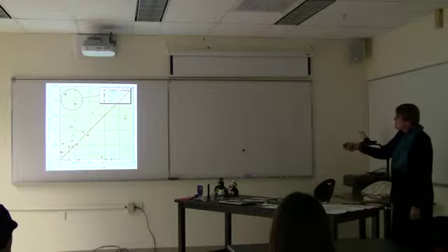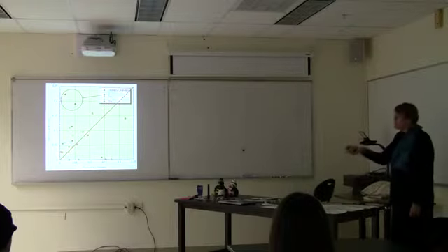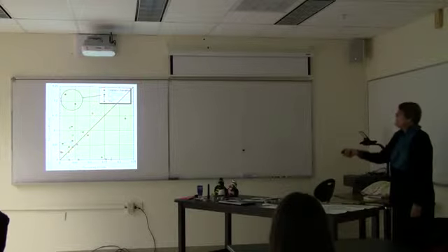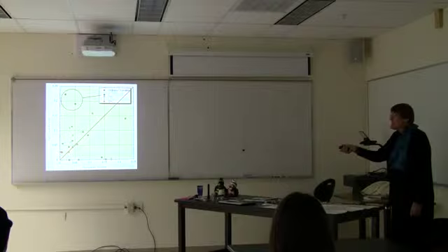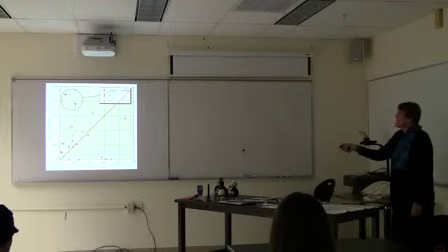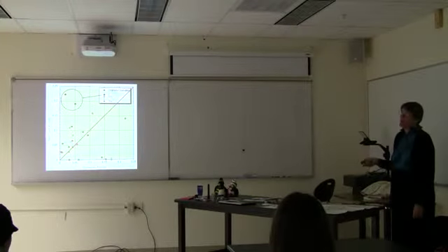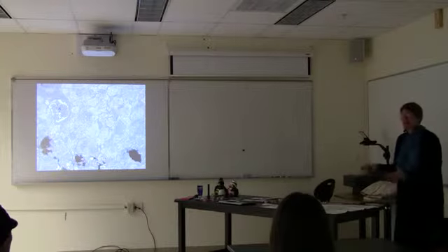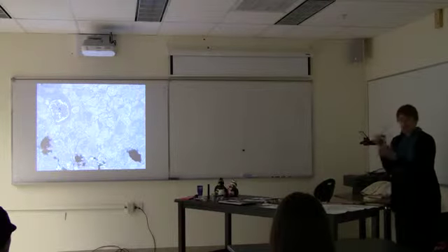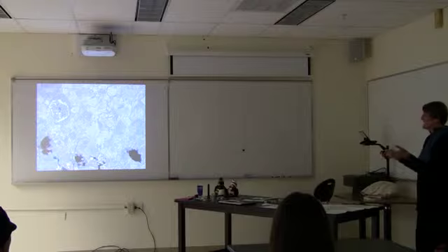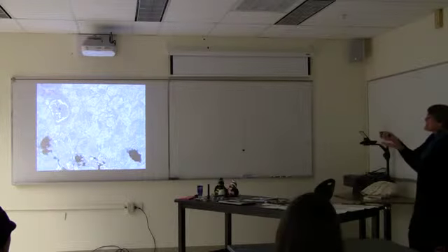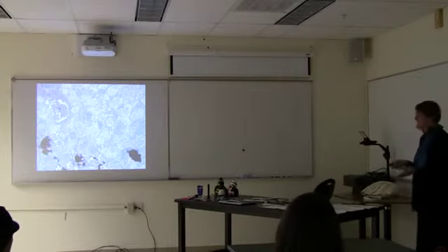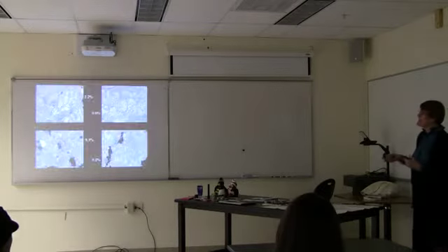And finally, then, the biggest problem we still have remaining is the carbonaceous chondrites. And this is a huge problem. I measure them up to maybe 5%. I can get a few individual images that approach 10%, but they tend to average less than 5%. Helium pycnometry shows 20 to 25% on a regular basis. You look at the picture, that is not 25% porosity. And if you look at that particular image, it is 3.2% porosity, which was high for that particular sample.